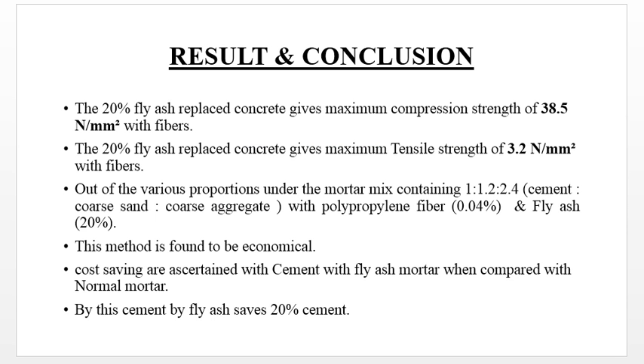Our graph shows that the 20% fly ash with fiber gives the maximum compression strength. Result and conclusion: the 20% fly ash replaced concrete gives a maximum compression strength of 38.5 Newton per mm square with fiber, and the 20% fly ash replaced concrete gives a maximum tensile strength of 3.2 Newton per mm square with fiber.